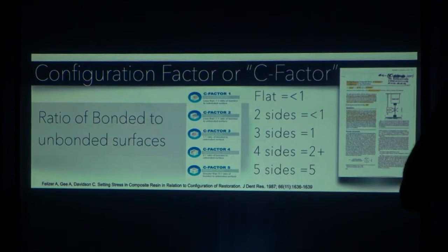But this experiment was also done with chemical cure composite, which allowed more flow during that 5 minutes. But in a natural tooth with a hierarchy of bondability, there is always going to be a price to be paid if you try to use chemical cure composites. Because that 5 minute mark is the same as a 1 minute mark with light cure composites. So there's five times as much interaction with this hierarchy of bondability with a chemical cure than there is with a light cure.